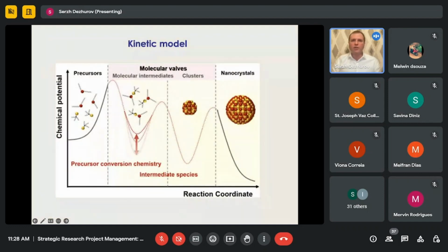About the kinetics of formation of quantum dots. First, you have a mixture of precursors like metal and chalcogenide like sulfur or selenium. The first stage is creation of molecular intermediates and clusters, very small creations. This process depends on the temperature and concentration of your precursors.